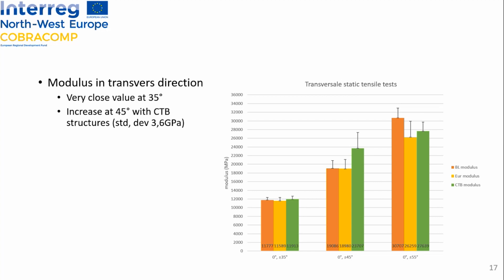The same test, but in the transverse direction. That means the coupons are cut perpendicularly to the UD yarn direction. That explains the decrease of the value compared with the axial direction. But in the transverse direction, mechanical performance is brought by the bias yarn. And we can see that the interlock structure seems to lead to more mechanical resistance at 45 degrees compared with the baseline and classic triaxial samples.